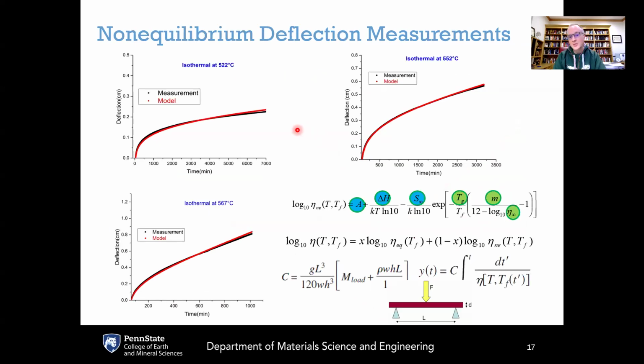The next step is to get the parameters that are needed for the non-equilibrium glassy state. These viscosity measurements are conducted by beam bending experiments where you put a beam of the glass in a 3-point bending configuration and hold it at different isothermal temperatures in separate experiments. These are isothermal holds at 522 degrees C, 552 degrees C, and 567 degrees C. Holding them over time, the deflection is measured as a function of time. That deflection data is used to back out the viscosity by this equation. And then that viscosity versus time and temperature data is used to deduce the parameters for the non-equilibrium viscosity model.